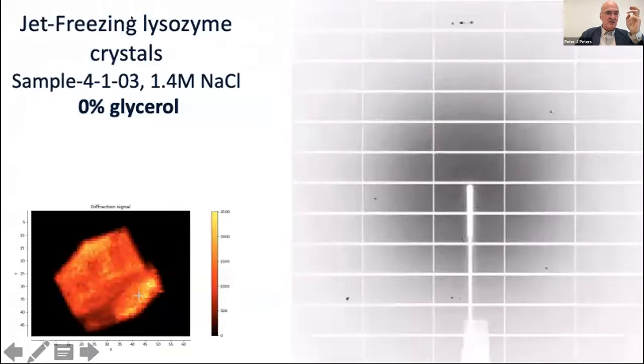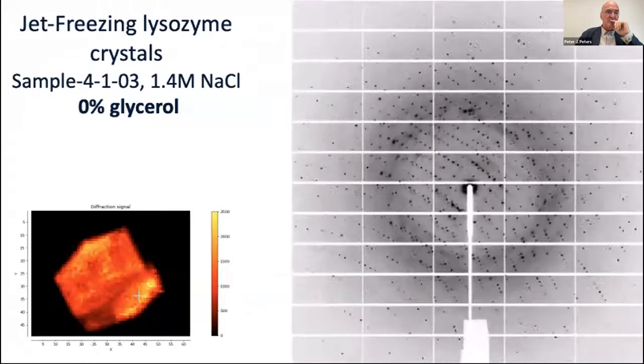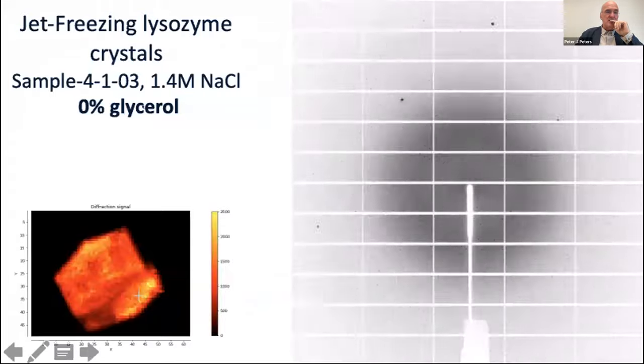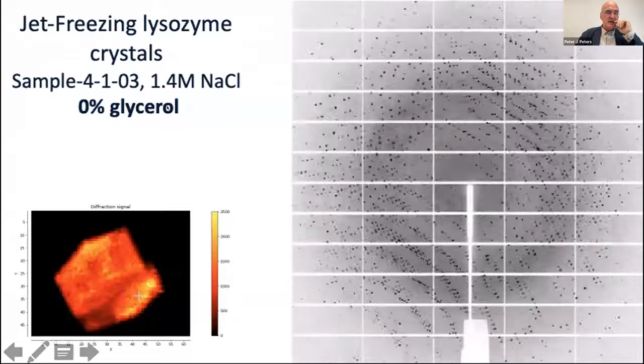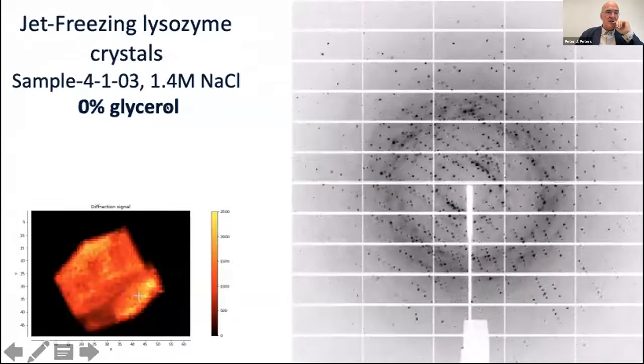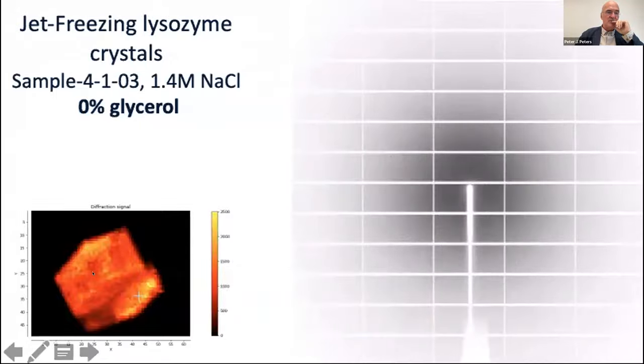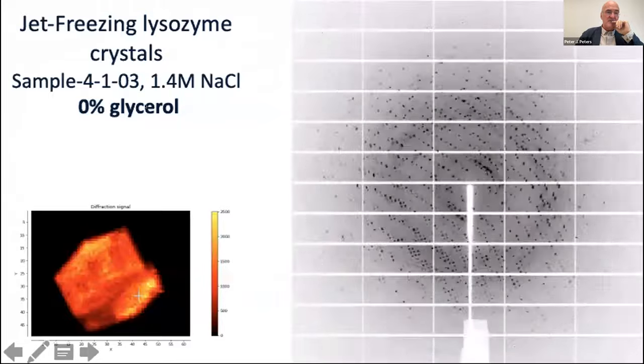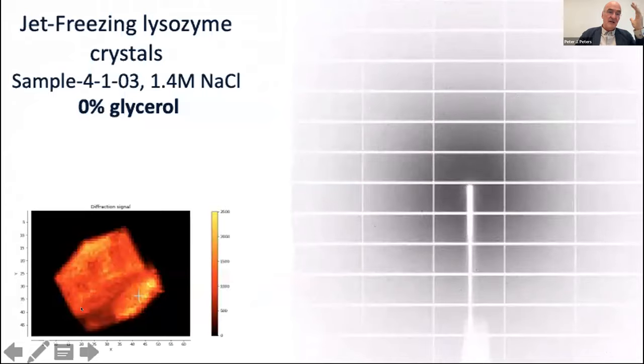This crystal is in this case lysozyme, but you can take any one that you want. And we vitrify this now without any cryoprotectant. Usually X-ray people need cryoprotectant in order to vitrify crystals. These cryoprotectants may have side effects. They may distort a little bit the crystal. But in this case, we can vitrify the sample just in a salt solution without adding any cryoprotectant.